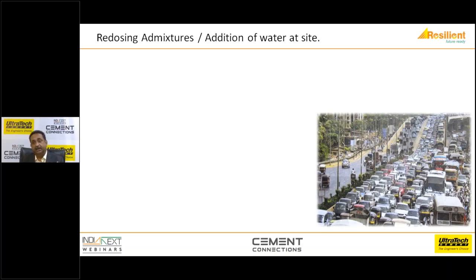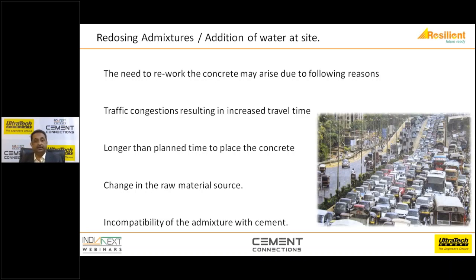Normally, a ready-mix supplier designs for the retention of workability based on how much time it takes to transport the concrete and how much time it takes for placing the concrete. And then they put a margin on top of it. But sometimes what happens is that there may be unpredictable traffic which delays the arrival of truck mixers. The site may not be prepared, and there's a delay in actually starting the concrete, or even the placing may have hampered.